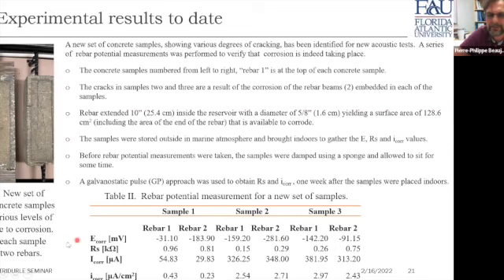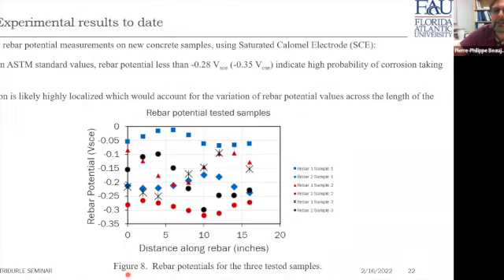So here are the values that are actually found as a function of the sample number and the rebar. So these are the coefficients E core in millivolt, R sub S in kiloohm, I core in microamps, and the last term, which is lower-case i core in microamp per centimeter square. Now, I do not have time to provide the detail of what these coefficients mean, but they are quite common in the field of potential measurement.